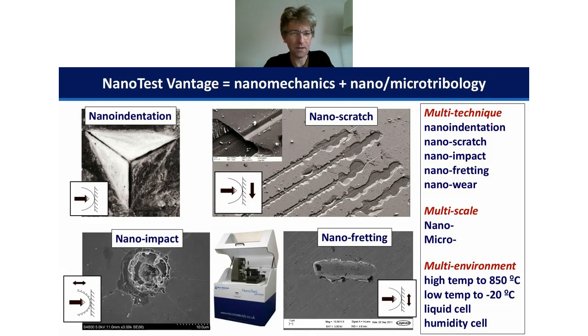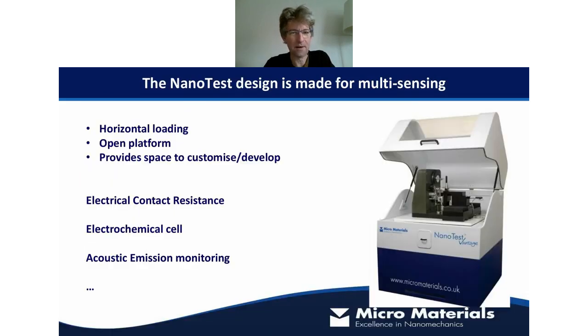So normally that's what I think about when I'm thinking about multifunctionality, but in fact we can get a lot more out of this system if we think about adding in a multi-sensing capability, so more multi-sensing tests essentially. The Nanotest Vantage is a horizontal loading system with a very open platform design, and this provides the space to customize and design different types of tests. Some of the things that we've developed over the years are the ability to look at electrical contact resistance, look at electrochemistry, as YT just talked about, and also acoustic emission monitoring while we're looking at either indentation tests, scratch tests, or impact tests, for example.